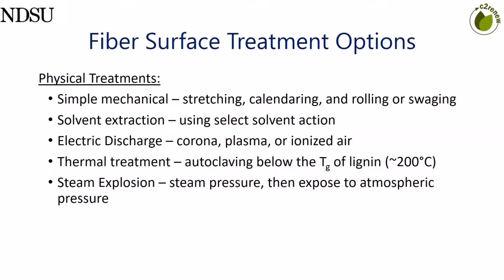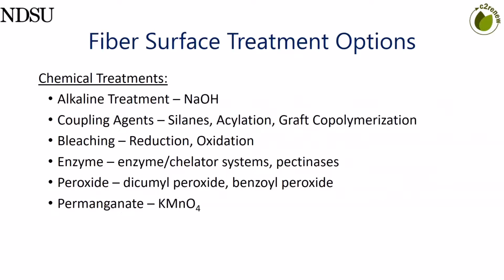Solvent extraction. We've tried electric discharge, plasma type of treatments, which have some effect. They're not long lasting, but they can excite that surface so that you can apply your resin or your coating and have a better inherent bond between your resin and your fiber. Some thermal treatments to decompose some of those lower molecular weight natural polymers, the pectins and the waxes, so we've tried some autoclave treatments. Steam explosion is another route.